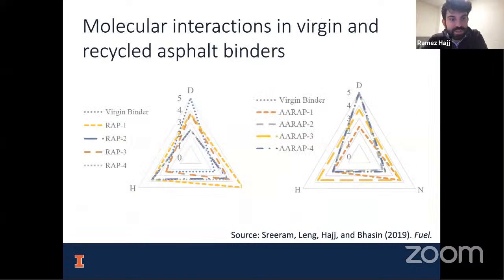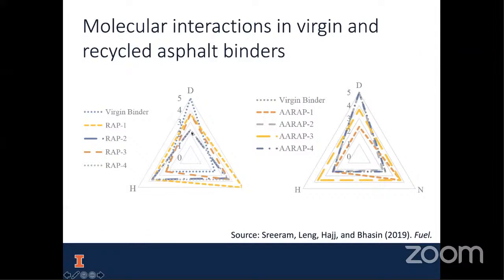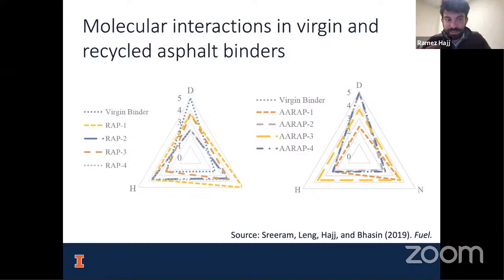And we did some study of this. We looked at many different RAPs, and you can see the D here represents dispersive forces. You can see that virgin binder, of course, is ranked a 5 if you normalize it this way. And then you can see different RAPs, some have less than half as much capability to disperse. So this is a huge problem because, again, that means the material is very stiff and very difficult to work with. And you can see here that the RAP also varies quite a bit.